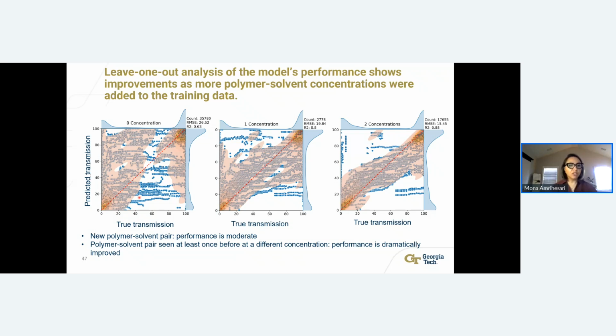When the concentration is 0, as you see here, the R-squared is 0.63, but as we increase the concentration of the same material to the model, then the accuracy also improves to 0.88 for only 2 concentrations. This shows how important some of these parameters, like concentration and temperature, are in training a machine learning model when we are talking about a phenomenon.